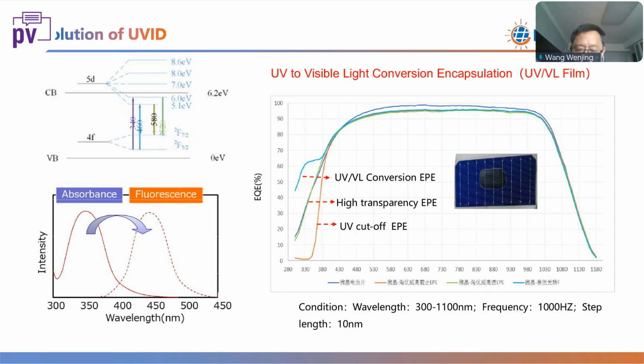So if we use a different encapsulation film, the QE is quite different for the module. If we use the high transparency EPE, the QE is like this. But if we cut off the UV wavelengths, maybe it becomes stable, but the QE in the short wavelengths will go down very fast. If we use the UV to visible conversion film, it can convert these short wavelengths to longer wavelengths, so it can increase the response and the current.